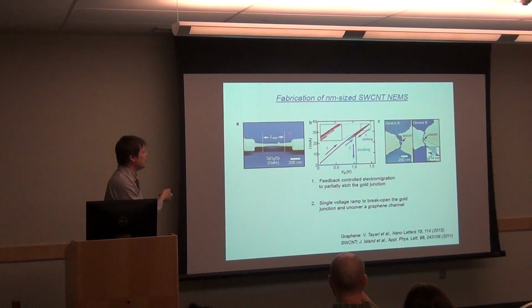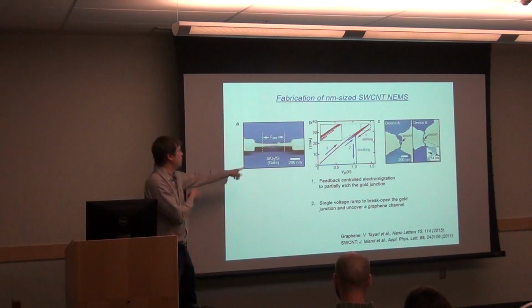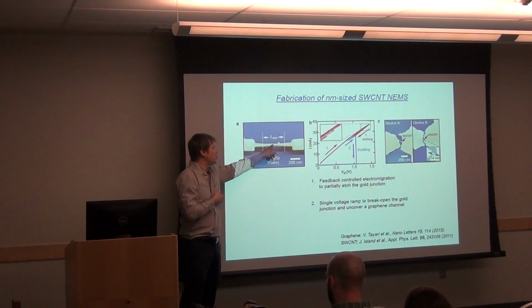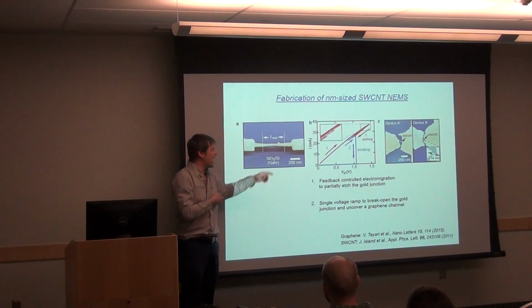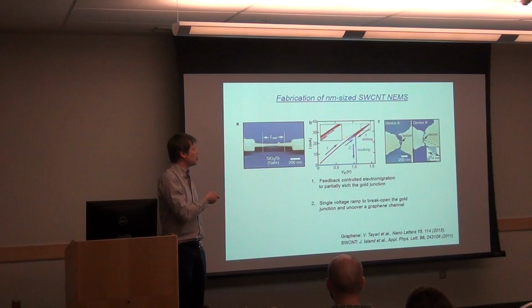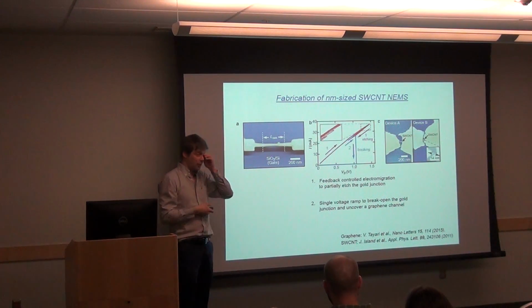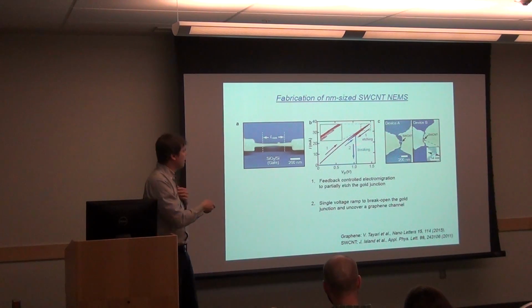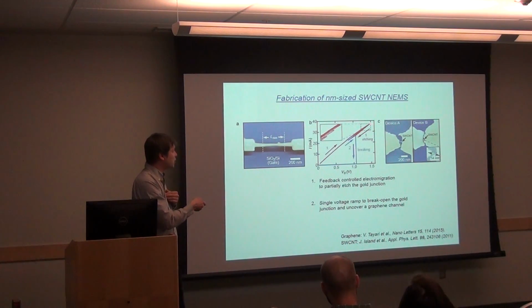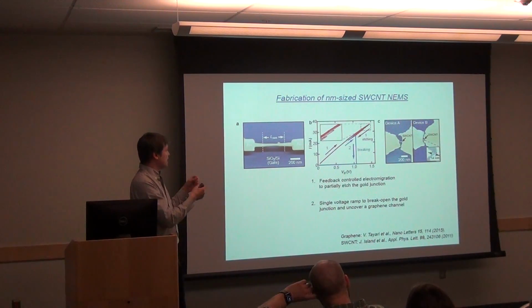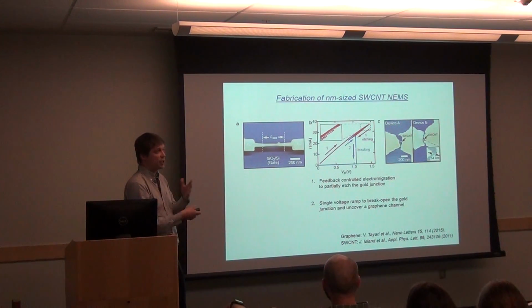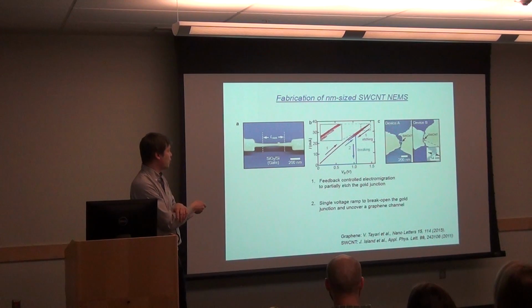Okay, so the last point is how to actually build this. I didn't tell you a lot about how you can actually open up this gap. We have a procedure where you apply an electric field across and monitor the resistance of the bridge. Once the current starts to decrease, meaning the resistance increases, you know it's starting to etch. So you don't want this to be an avalanche process. You ramp down the voltage and then back up and down.